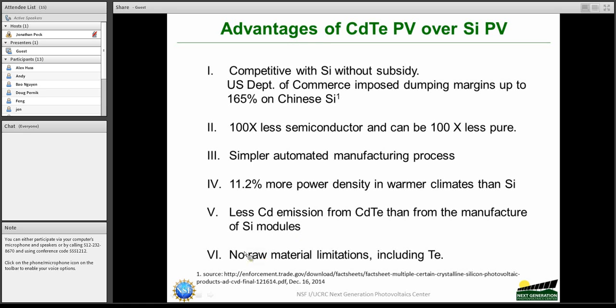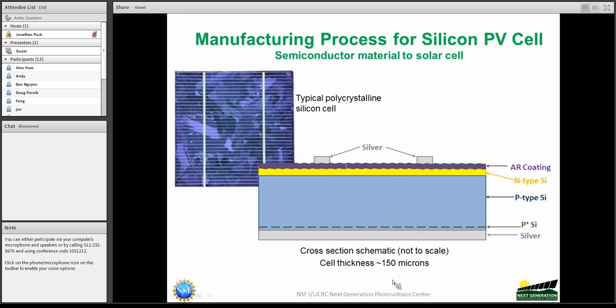And this is because the energy requirement for making silicon modules is quite high, and currently, the way we produce our energy, if you take an average, the amount of cadmium emission from producing that amount of energy is more than the amount of cadmium that is encapsulated in the cadmium telluride modules. Initially, there was a concern about raw material limitations, but currently those are not considered to be limitations at all, and this includes tellurium, which is somewhat rare, but there is enough being found and discovered to use it for the needs.